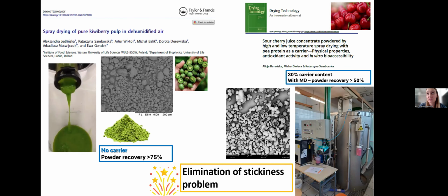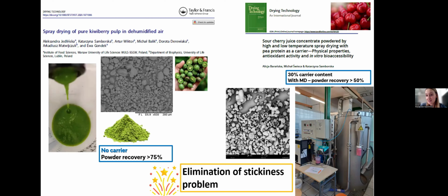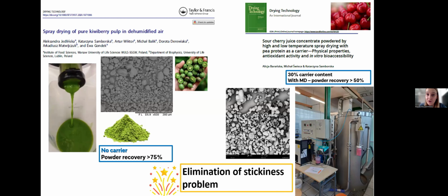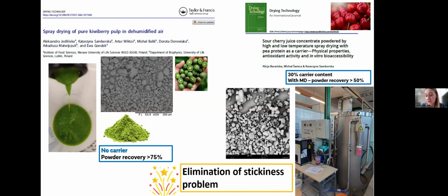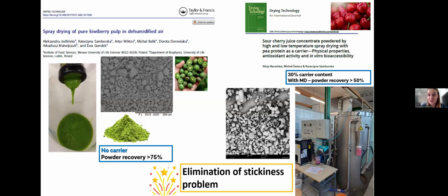With sour cherry juice concentrate, which is a very difficult material to be spray dried because it contains a significant amount of low molecular weight sugars, but as well a high content of organic acids, it was not possible to eliminate the carrier completely. However, it was possible to reduce it significantly, especially in comparison to what we could observe in the studies over the years on sour cherry juice concentrate. Normally, it was 50% of carrier per solid, but by reducing the air humidity and drying temperature, we reduced the carrier down to 30%. And with maltodextrin as a carrier, we noted a satisfactory powder recovery, over 50%. So what can be taken from these studies so far is that we eliminated the stickiness problem due to air dehumidification.